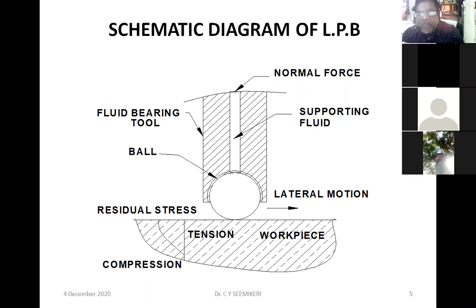Therefore, my other friend of surface enhancement is basically shot peening. In shot peening, the ball is hammered on the surface. Though we are inculcating fatigue strength, the amount of deformation is very large, thereby the word that is used, cold working. I think everybody knows this. Cold work is very large, around 25 to 30% more than in other methodologies. Here, cold work is less than 5%. Therefore, the beauty of LPB burnishing is lesser cold work, lesser deformation.